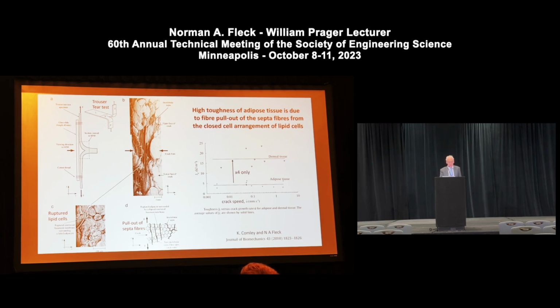and the dermis and the sub-layers of fat. And what you find is, for the case of adipose tissue, if a crack is formed by a trouser tear test as shown, and if you look at the crack path, what you see are stretched out fibers. Looking at the crack tip region where it stretches out, here are the stretched out fibers. They eventually tear and pull out. The cell walls of the closed cell foam burst and a crack advances. That's the mechanism of toughening which occurs, the pull out of the fibers in the case of adipose tissue.